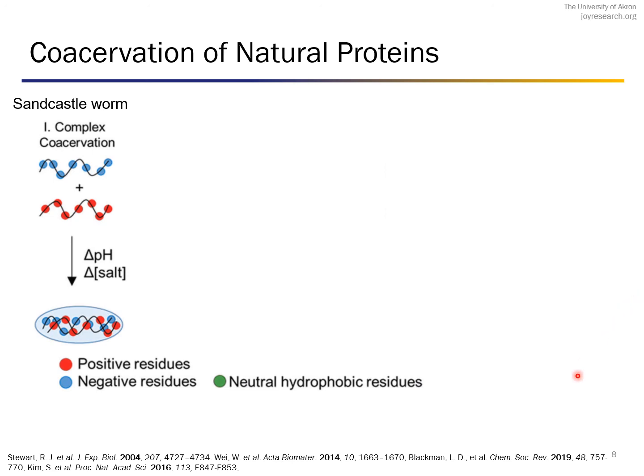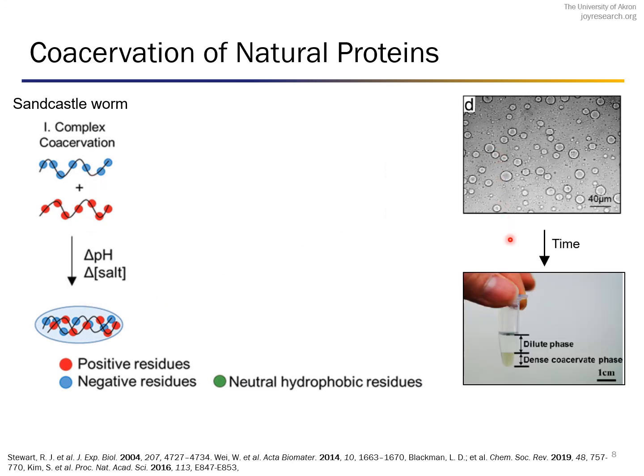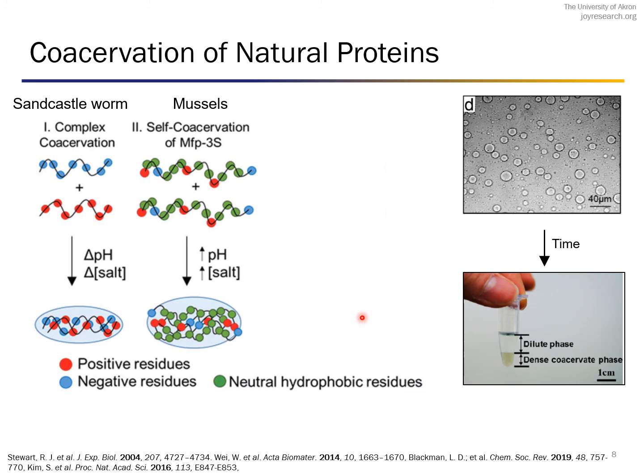Another aspect which is very important for these bioinspired adhesives is their delivery. So sandcastle worms have a special way of delivering their adhesives. They secrete a series of positively charged and negatively charged proteins, which when mixed together at a neutral pH form droplets like these here, and with time it settles to form two different phases, known as dense and dilute phases. Recently, mussels also have been shown to have this mechanism to deliver their foot proteins. The interesting part about mussels is their ability to self-coacervate, which means it only needs one component. These are two identical components, and it forms coacervation even without a secondary mixture like the sandcastle worm.